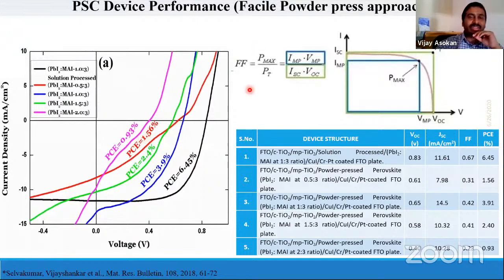With those different structures, of course, we have used different hole transport layers with our materials. For example, we have used copper iodide or copper iodide and chromium platinum coated FTO, or here copper iodide chromium with our powdered perovskites with different molar ratios, 1, 2, 3 types or 4 types of different molar ratios of methyl ammonium iodide and lead iodide, and try to measure the power efficiency.